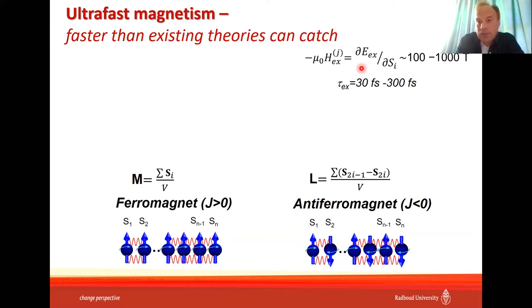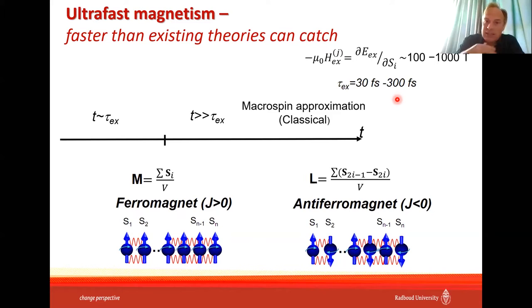And if you take these magnetic fields and calculate the period of Larmor precession of spin in these fields, then you will get times from 30 femtoseconds to 300 femtoseconds. Now, if you start to think about spin dynamics, keeping in mind that the characteristic time of the exchange interaction is between 30 and 300 femtoseconds, then if you consider spin dynamics on timescales much larger than that time, you can indeed use the macrospin approximation, assuming that all the spins are pointing in one direction and the exchange interaction that brings them all together is much stronger than anything else in the sample.